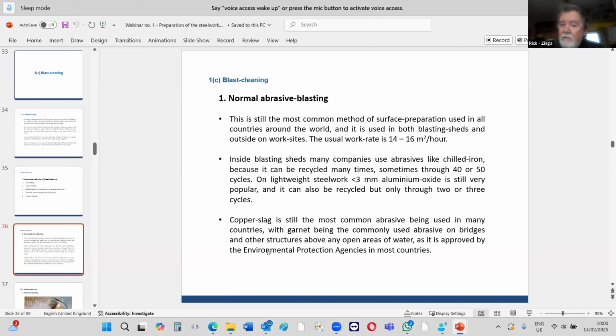When you buy the chilled iron, you can reuse it and reuse it and reuse it. And as I say here, 40, 50 cycles. And each time it hits something, bits break off. But those bits are sharp, so they still have cutting power. So you can recycle and recycle. And if you have a measuring gauge, you simply measure your depth, which you do anyway, before you apply the Zinga. And when you see your profiles are getting shallower, you simply buy a couple of bags and you add it into your pot, okay?